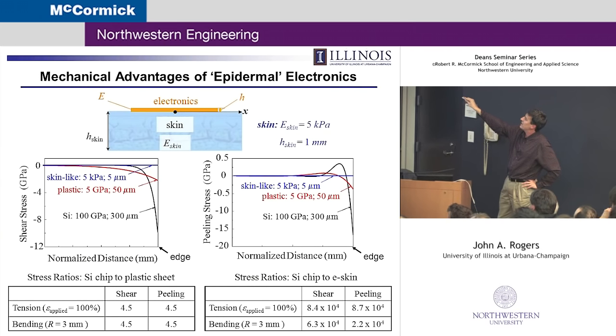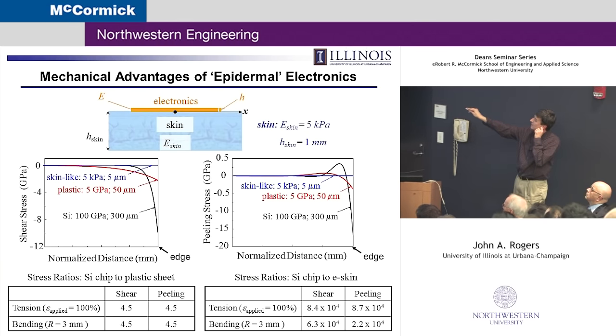So just think about this construct. You have a piece of electronics, modulus E, thickness H, sitting on a piece of skin, modulus 5 kilopascal, thickness of 1 millimeter. And then think about what happens when you bend or stretch the skin. So think about stretching first. Yonggang computed the shear stresses that form at the interface between the silicon and the skin as a function of distance for different kinds of electronics, and the peeling stress, both of these being the types of stresses that can drive delamination.